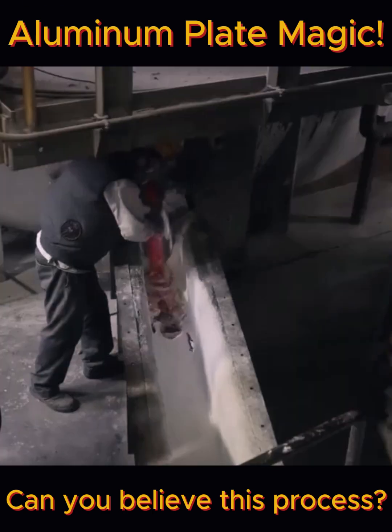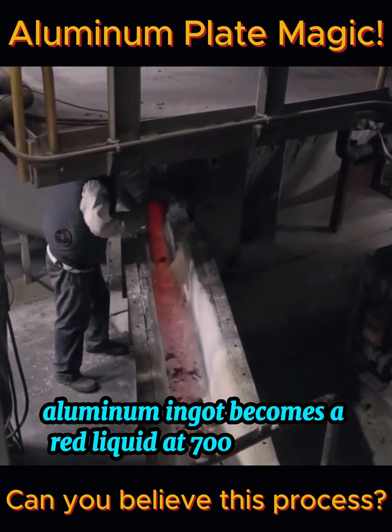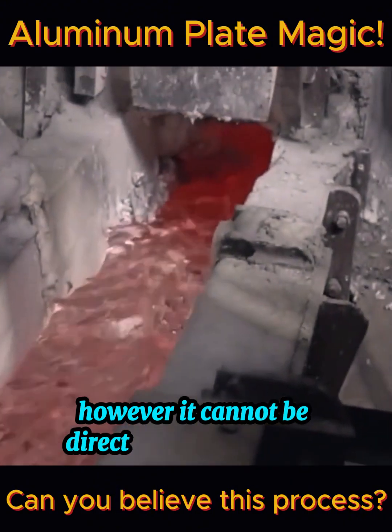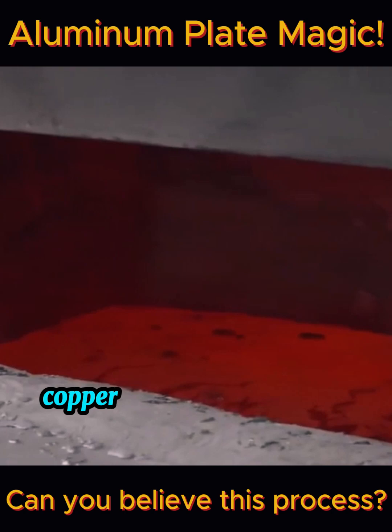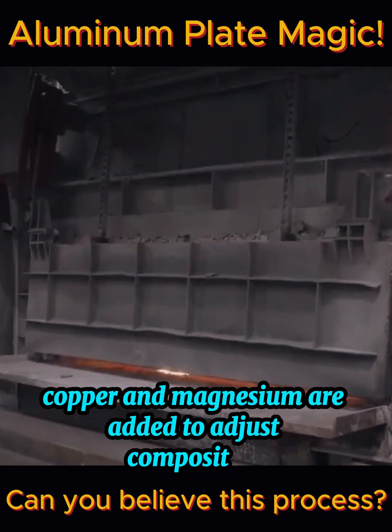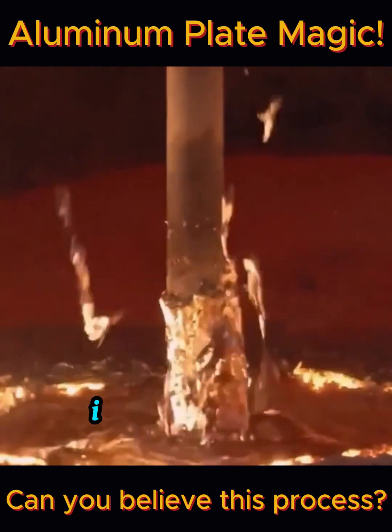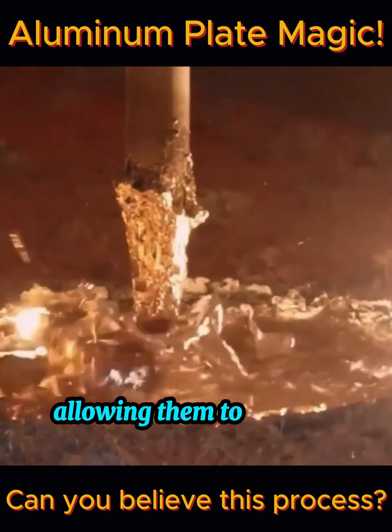After smelting, the aluminum ingot becomes a red liquid at 700 degrees C. However, it cannot be directly used for casting. It flows into a storage tank, where silicon, iron, copper, and magnesium are added to adjust composition. Once the aluminum ratio is set, equipment starts high-frequency slag removal. And this oxidizes the impurities, allowing them to float on the surface.